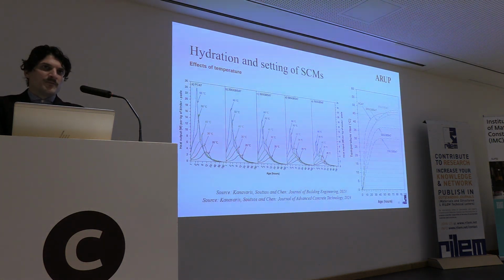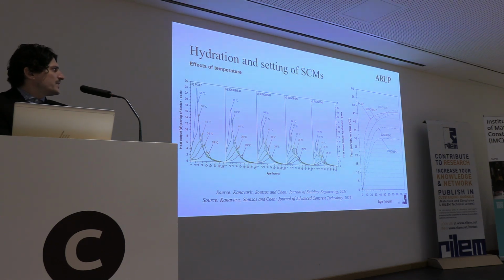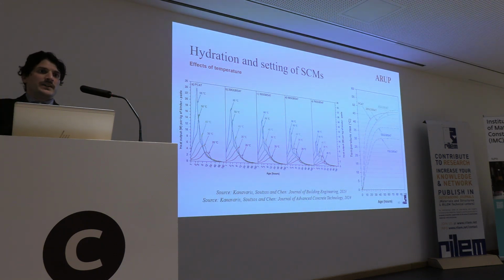And we generated very meaningful data in terms of the effect of temperature on the evolution of hydration heat of concrete cements with different supplementary cementitious materials, and really understanding, for example, slags that have been predominantly used in massive concrete structures to control the temperature evolution, what it means to have high curing temperature in terms of slag hydration. And we're seeing, for example, in very high replacement levels, the secondary reactions associated with slag are reinforced at very, very high temperatures. And equally on the efficiency of reducing the adiabatic temperature rise, which is relevant, resembles really a massive concrete structure. What is the actual efficiency of slag and GGBS in terms of reducing the temperature?